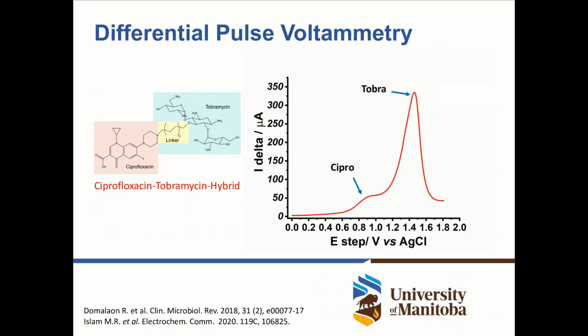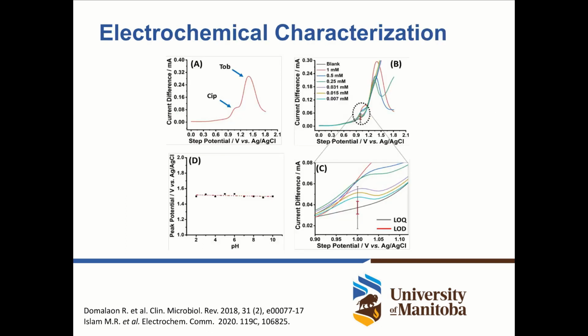And then in electrochemistry, we can define our parameters, such as how we apply the voltage in terms of duration, step height, and step width, which is called differential pulse voltammetry, to get a better resolution of these peaks. These peaks we can then use to quantify an analytical species in solution. Here in this figure, you see in figure B how we use this to determine limits of quantification and limits of detection for a certain species. And we can carry out these measurements at different pHs, as shown in D, where we assess how stable these measurements are across different pH values.